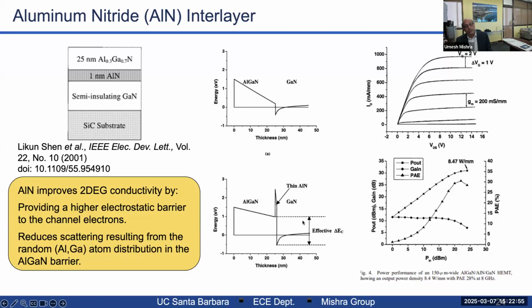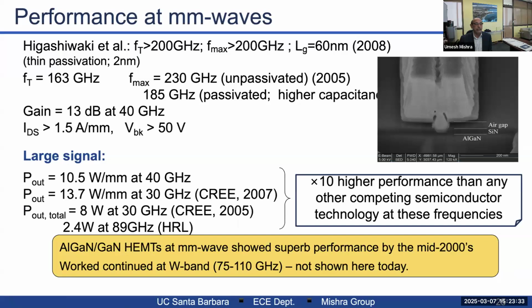So what you actually do is you can change the effective conduction band discontinuity, which is this delta EC, which is what nature gives us. And then you add to it the polarization voltage of the aluminum nitride, you get a huge increase in effective delta EC without changing the two terminal materials, AlGaN and GaN. And you get a higher mobility simultaneously with higher charge. So all of a sudden, we went from 4 watts per millimeter to 8 watts per millimeter. And this basically was a big breakthrough in the gallium nitride technology.